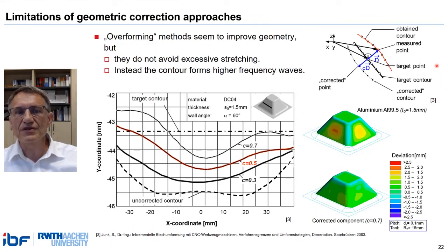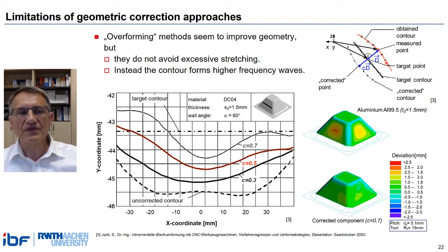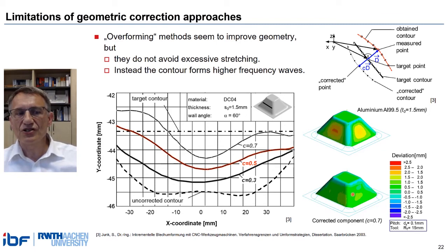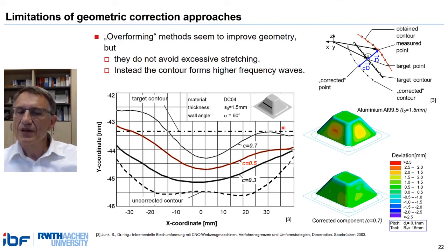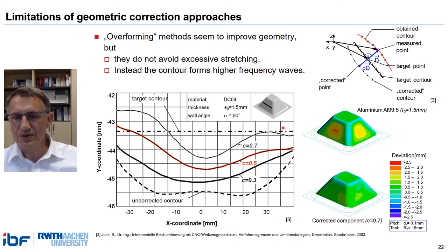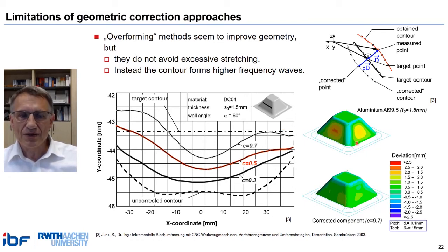Many authors have proposed various forms of correcting algorithms. Most of them are based on the idea of overforming, which is helpful to compensate springback in classical sheet metal forming. Also, this very early work from our group appeared to be helpful when not looking into too much detail. The general deviation could clearly be reduced and the bulge appears smaller. But looking into more detail, we see that the original bulge has been transformed into a higher-order wave. The reason is obvious: the bulge is a result of excessive in-plane stretch, which occurred even though the shortest possible tool path was used. Why should a longer overforming tool path lead to less stretch? So the algorithm reduces symptoms, but it does not heal the reasons.